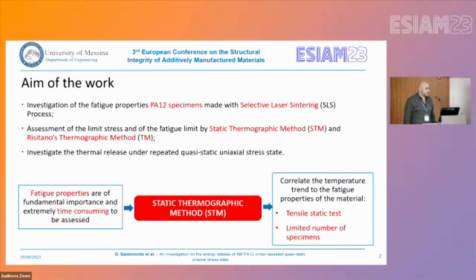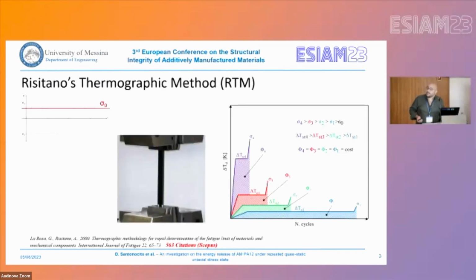For traditional materials, the first application of thermography was the Risitano thermographic method. And more recently, the static thermographic method has been applied also to additive manufactured materials to derive the first damage that we introduce in the material. So the basic idea of this methodology is to just perform short tests adopting a limited number of specimens. Briefly, I'll show you the Risitano thermographic method.